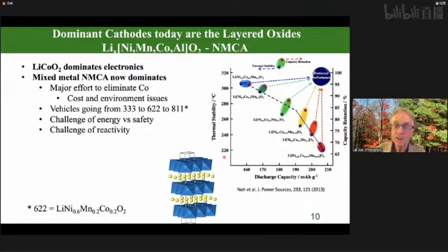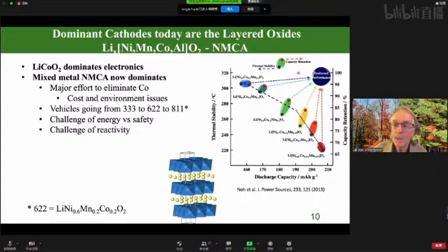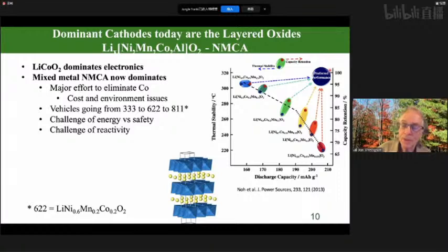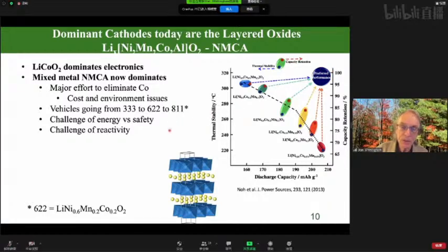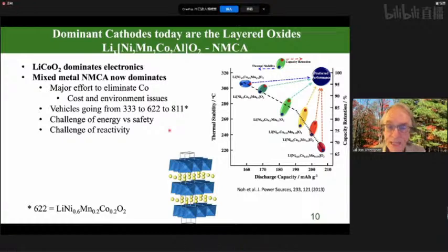And the thermal stability is really a measure of how reactive the materials are and therefore relates directly to capacity retention. So if you want high discharge capacity, you want very high nickel content. In this case, it's 85%. If you want high stability, we want low nickel content. This is about 1/3 nickel. Our goal is to get to this blue box, and I'll show you some of our work in a moment. So we have this challenge of energy versus safety, which really relates in the end to the challenge of reactivity.